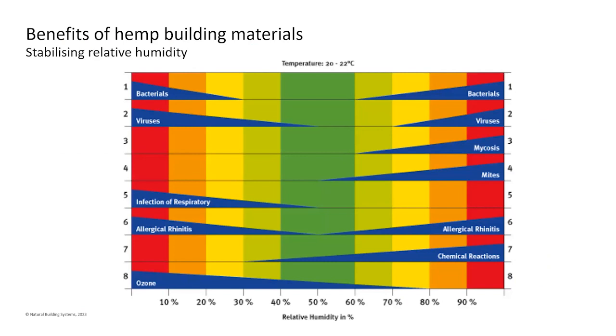One of the interesting things about using particularly hemp is its ability to moderate the internal environment of a building. It has a very interesting pore structure, and I've got some images of that in a minute. What it tends to do is, if you get a very high humidity in a building, it will suck that into the walls. And if it goes very dry, it will push the humidity out. So you maintain a really nice steady level of about 50 to 60% relative humidity.